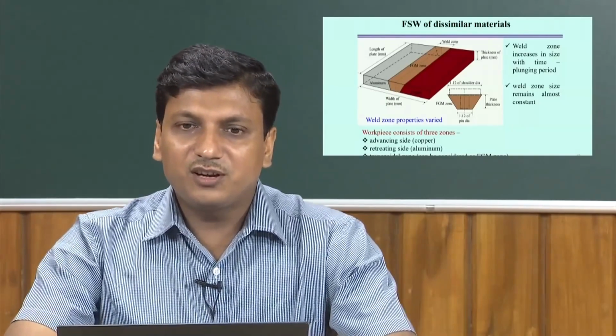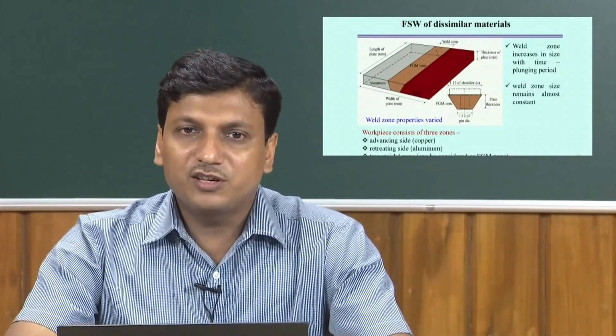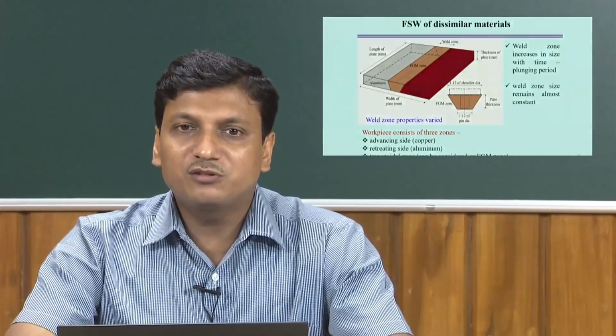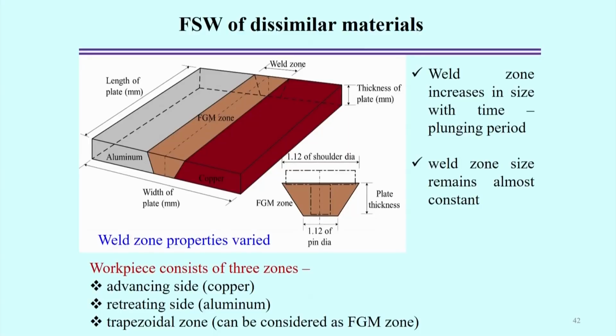Here, the typical size of the functionally graded material zone is 1.12 times the shoulder diameter on the upper side, and 1.12 times the pin diameter on the lower side. That means it is just above the diameter of the pin and of the shoulder, and the shape is more or less triangular. So, to analyze the hybridizing of the friction stir welding process, specifically for dissimilar material, they create these different kinds of zones.